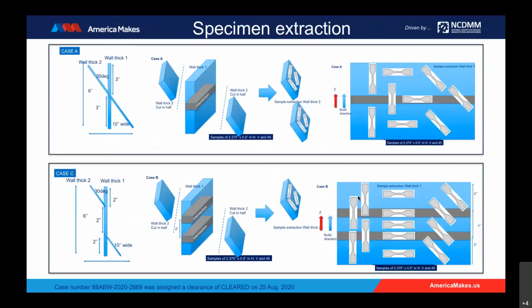So we had two kinds of intersections, which you could call a continuous X and a segmented X. So case A and case C are shown here, the two different intersection designs. For the overhang features, we cut off the side inclined portions and cut specimens out of it. And to assess the influence of the intersection, we cut specimens at different orientations within the vertical trunk of the wall. And for the intersection region, we had the tensile coupons' gauge length lined up as need be with the intersection region. So here in case A, you have the effect of building two intersections in that intersection union region. In case C, you have the effect of building one intersection in the intersection region. Similarly, the building of this overhang also affects the intersection region differently, and that was captured in the model setup as well.